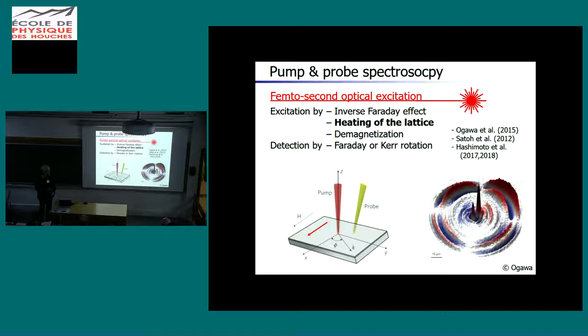And you get pictures like that, where you throw a stone basically into the pond and you see how the waves are moving outwards. Now the excitation can be done in principle by three processes: the inverse Faraday effect, which is not important here because the experimentalists do not see a difference between plus and minus polarization. It can be heating of the lattice, which is our favorite model. We cannot completely exclude that there might be some contributions to demagnetization by the laser. Again, detection is now standardly done by Faraday and Kerr.